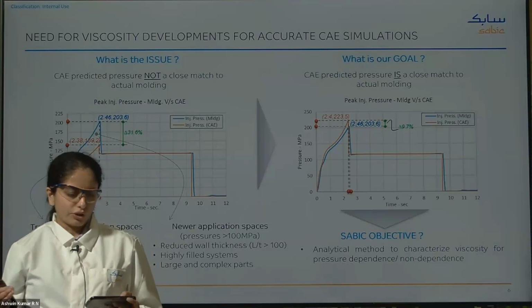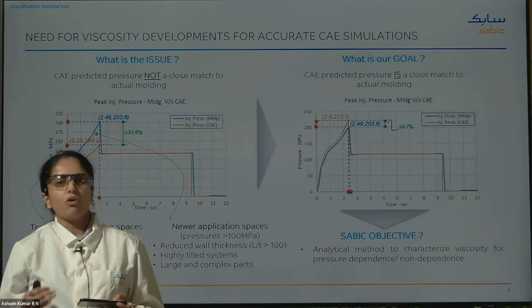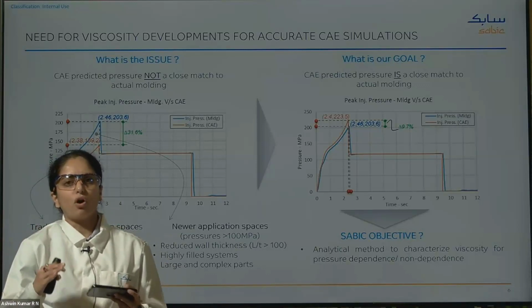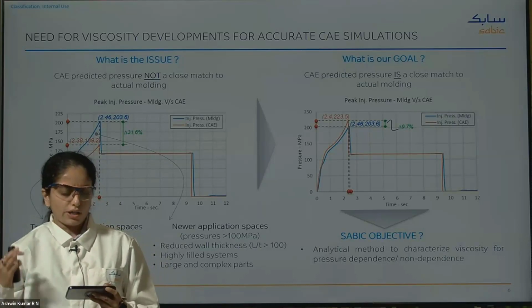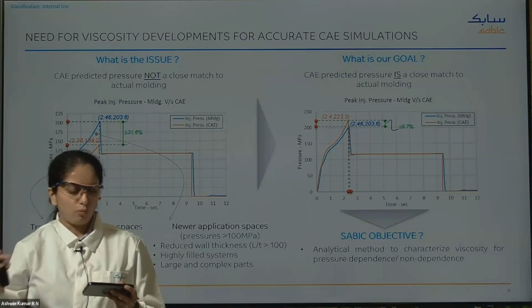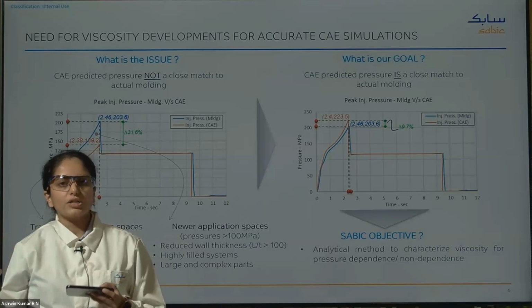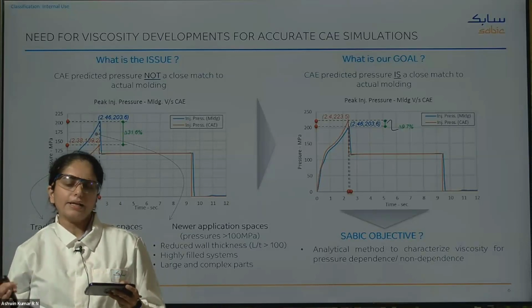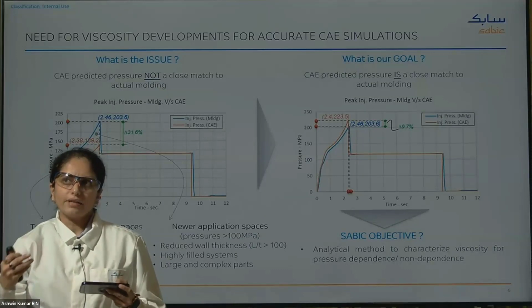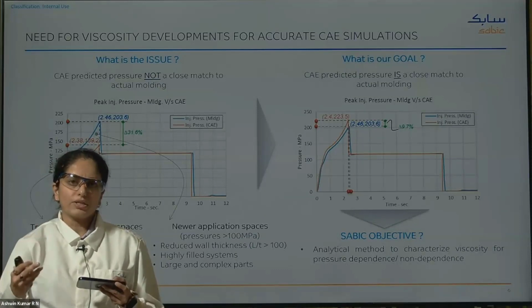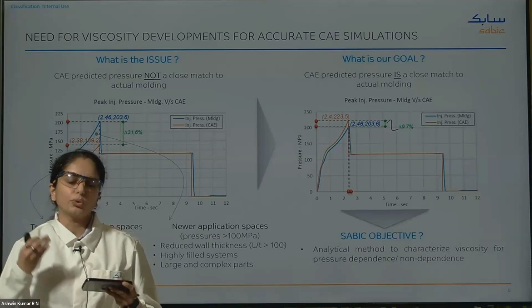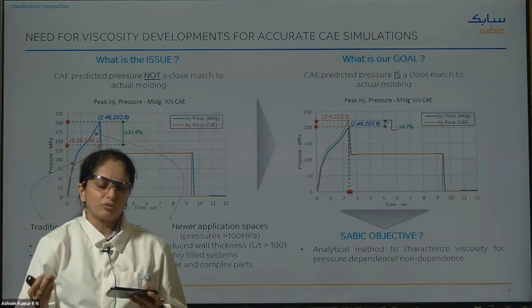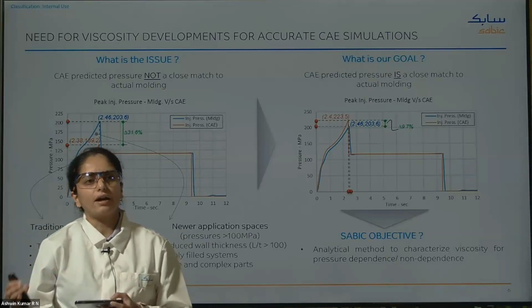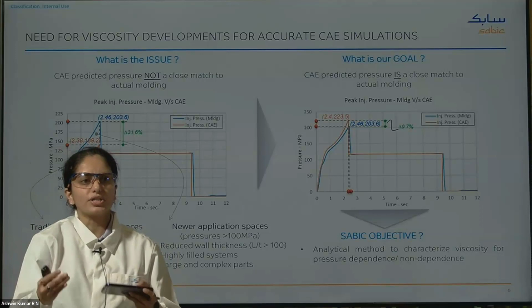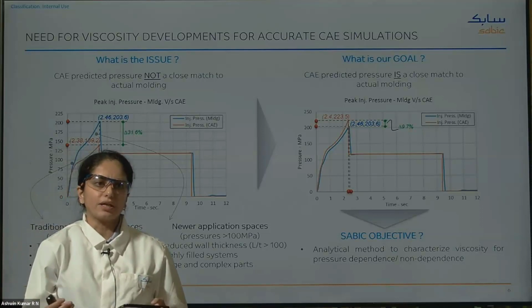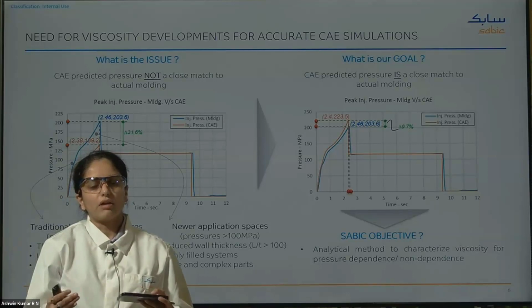So a comprehensive rheological characterization is required in order to understand the influence of not only shear rate and temperature, but pressure on injection molding. The Cross-WLF model is widely used in simulation because of its simplicity. And what does the D3 parameter tell us? It tells us about the changes in glass transition temperature due to the applied pressure and the increased melt viscosity. In most material data cards that you will encounter, you will find that the D3 parameter is either missing or not evaluated at all.